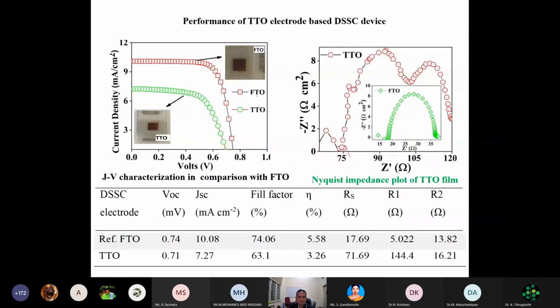Okay. So when I come to the efficiency of my device, this is a device which we fabricated, and you can see what the efficiency of this device is. When I use a standard fluorine doped tin oxide, a commercially available material, as an electrode, the efficiency is 5.5% power conversion efficiency. For my TTO, it is showing 3.26.